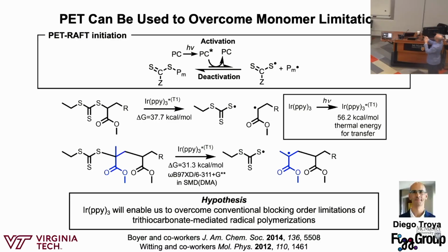But what's important is that both of these are quite a bit lower than the amount of energy that the iridium actually has for energy transfer. So our hypothesis was that if we use iridium ppy as a photocatalyst, because its amount of energy available for energy transfer is so much higher than either one of these, it's essentially going to be agnostic to whatever the chain end is. It's just going to get excited and then react with whatever polymer it finds. It's not going to be as selective because we're so much over either one of those bond dissociation energies.